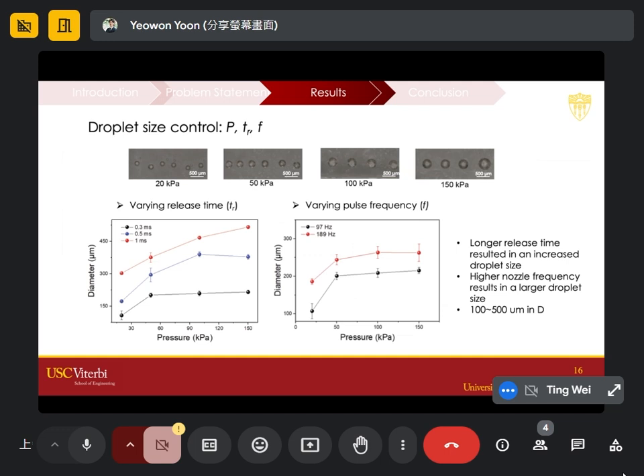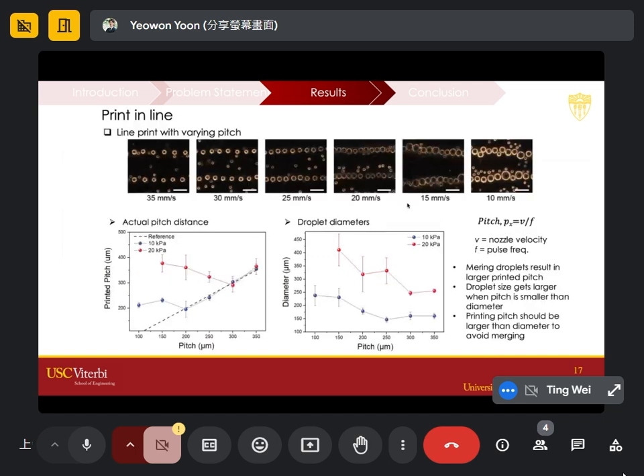If we go from 0.3 millisecond to 1 millisecond, we can see the droplet size increases, also with increasing pressure. The varying frequency means how often you're creating the jet stream, and the faster it is, the bigger the size of the droplet that it creates. But after some point of pressure, the size saturates. So here we are able to create from 100 to 500 micron in diameter.